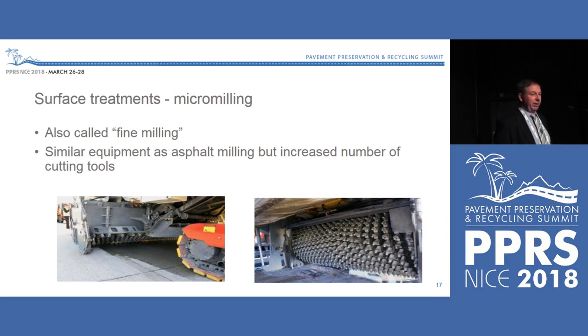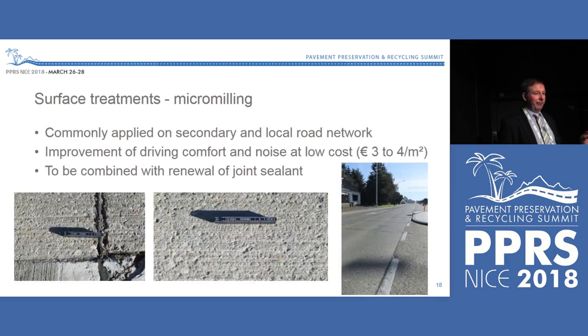First, you have the micro milling or fine milling. It's a similar equipment as for asphalt, but with a larger number of cutting tools, so that's why you get a real fine texture, and it's very often applied on the local road network. Very recently in the village where I live, all the old concrete pavements have been treated in this way, and I can assure you that there was a significant improvement. And interesting for the authorities is that this can be done at a relatively low cost. Obviously, it has to be combined also with renewal of the joint sealant.